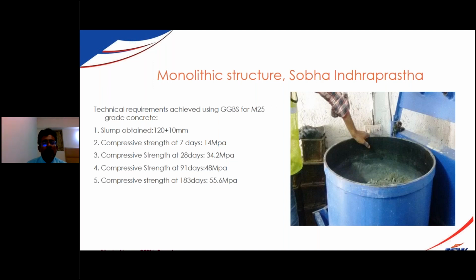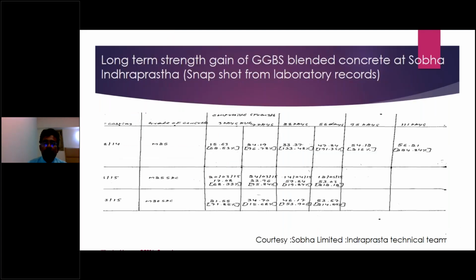So you can see the M25 grade concrete giving 55 MPa, almost double the strength of its original grade M25 over 183 days. So to make you believe, we have taken the screenshot when the details were maintained at their laboratory at site. So this is a handwritten document. So we have not fudged any numbers here. So M25 grade concrete becoming M54 grade.